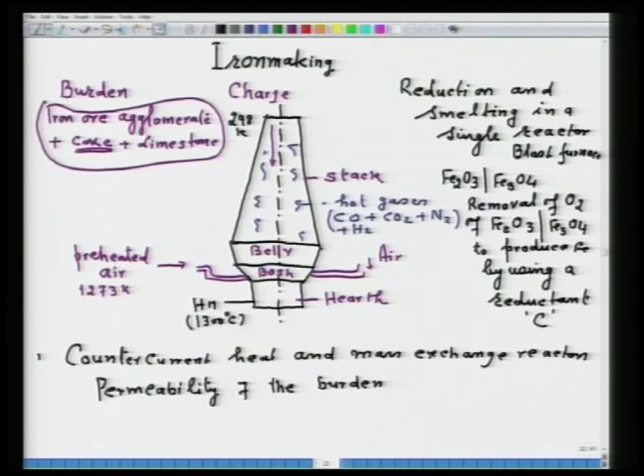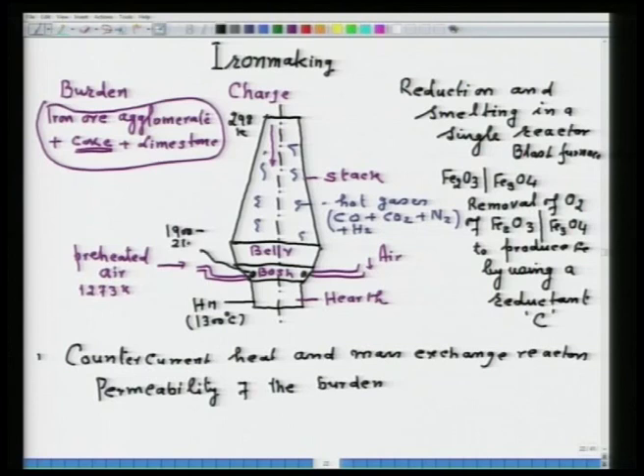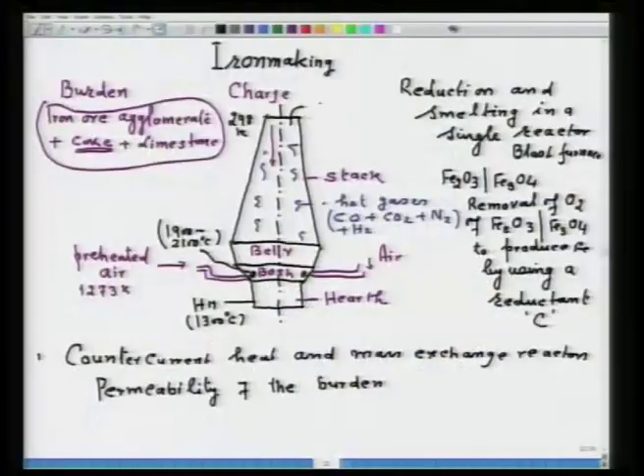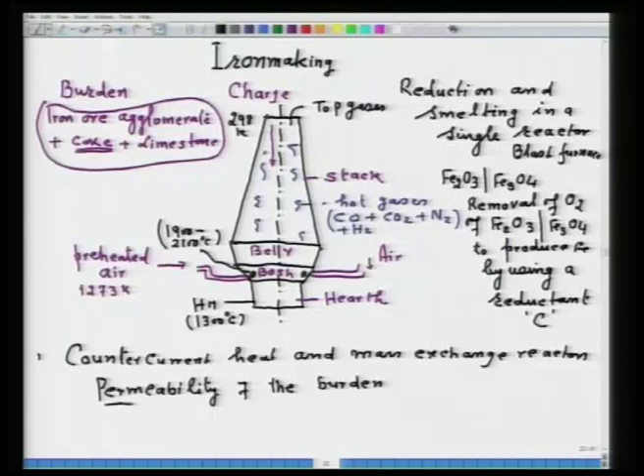At the point where air is injected and coke reacts with oxygen, a temperature of 1900 to 2100°C is created. When these hot gases rise upward, the bed or burden must provide sufficient permeability so that the gases can escape unhindered through the burden and exit at the top. At no point should the upward flow of gases be hindered; therefore, permeability of the burden is a very important issue.